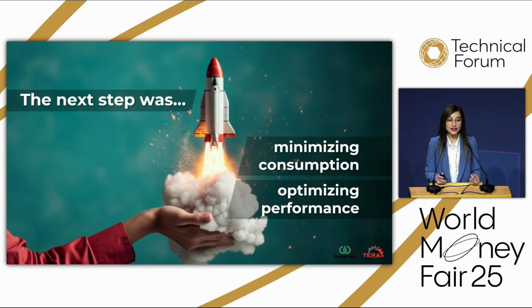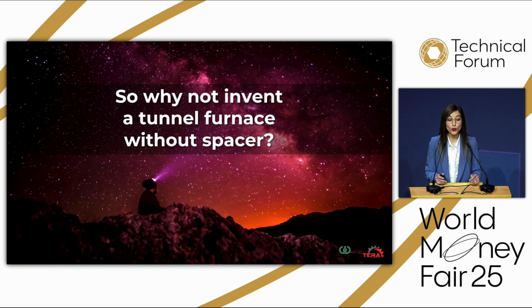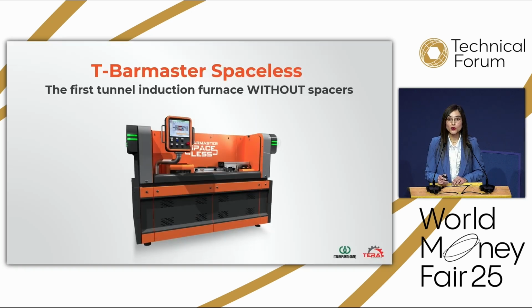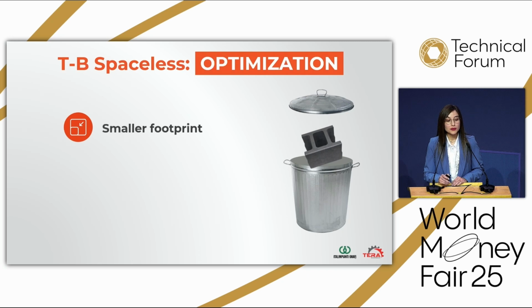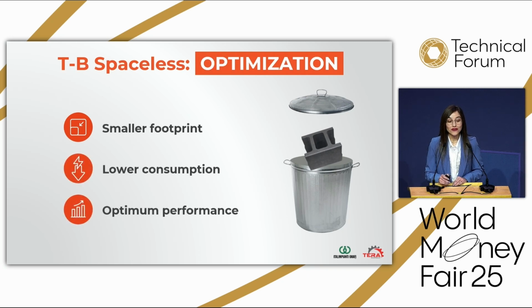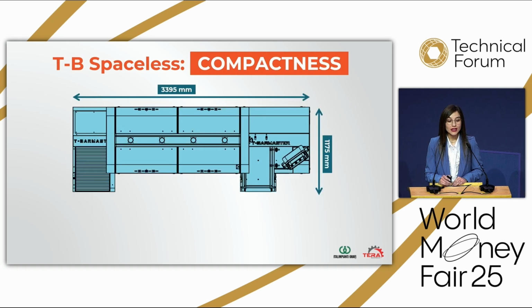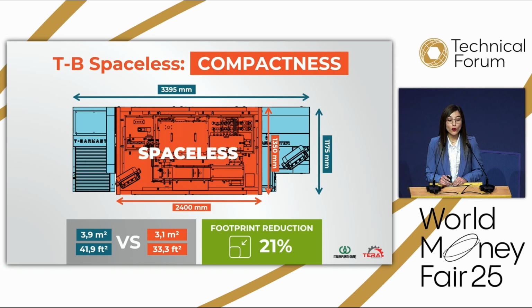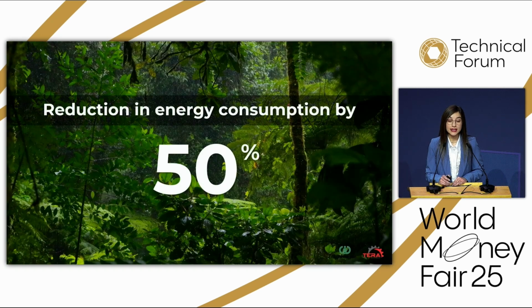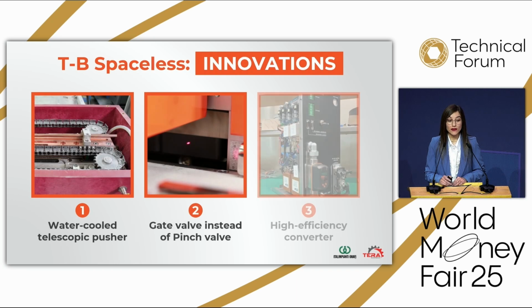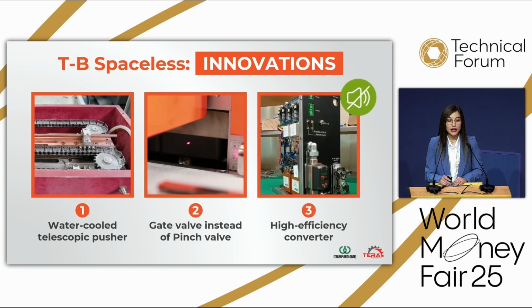This approach eventually led us to the question, so why not design a tunnel furnace without graphite spacers? So let's give space to our T-Bar Master Spaceless, the first induction tunnel furnace without graphite spacers. The spaceless concept is geared towards maximum optimization of traditional tunnel furnaces, which means smaller footprint, lower consumption, along with optimum performance. With this new version, we managed to reduce the overall footprint of the machine by 21% compared to the traditional equivalent T-Bar Master. What's more, it is extremely efficient, leading to a 50% reduction in energy consumption. The T-Bar Master Spaceless carries 3 major innovations: the water-cooled telescopic pusher, gate valve instead of pinch valve, along with a high-efficiency, completely silent and compact converter.